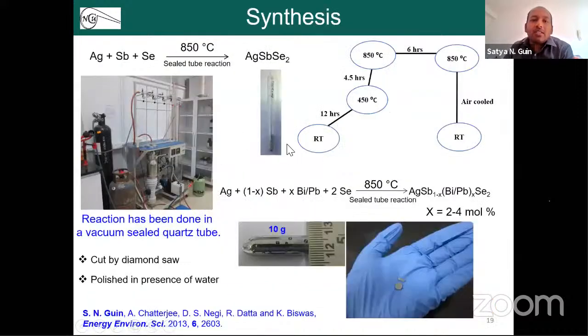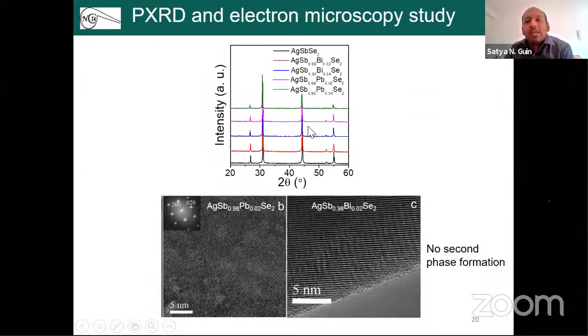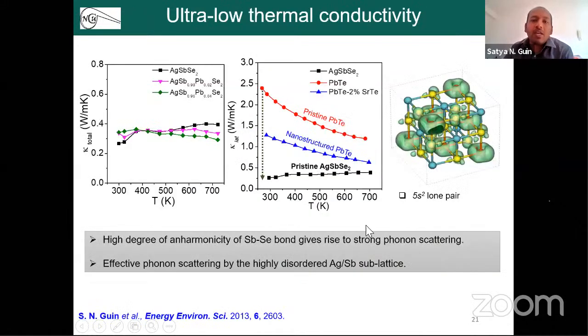So here is the synthesis strategy we have used for the pristine as well as for the doped samples. We use lead and bismuth and we can get a very nice ingot for the transport measurements. Then we cut it into bar and pellet shapes for further study. And these are some of the characterizations. As I told you, you can characterize by powder X-ray. You see the very nice single phase nature of the samples. And transmission electron microscopy also shows a very homogeneous nature of the samples. So from there, we started further measurements.